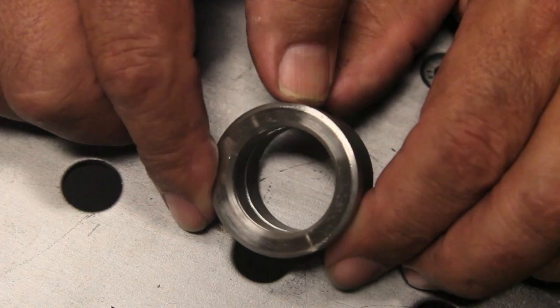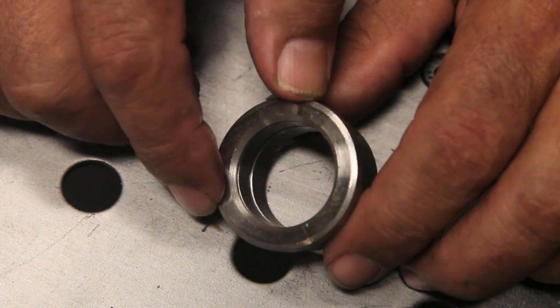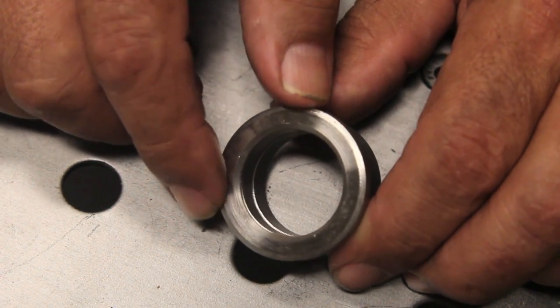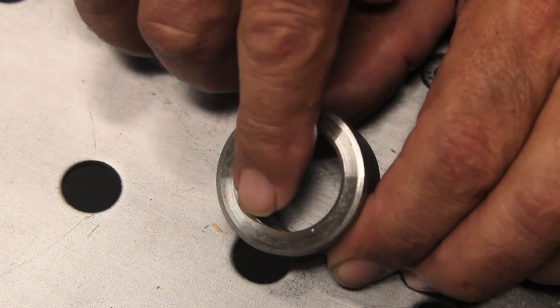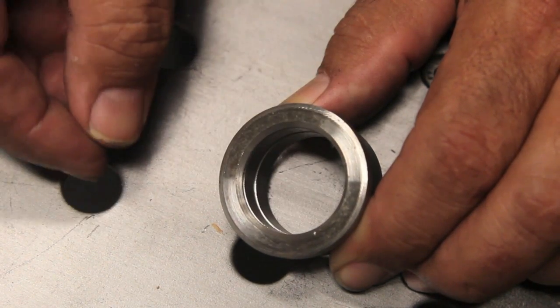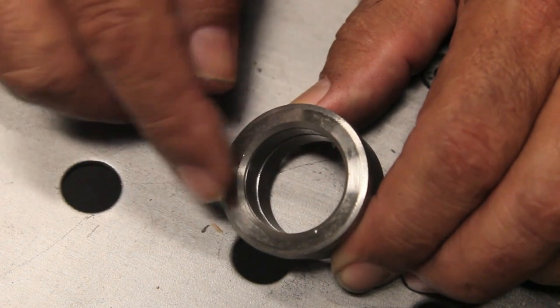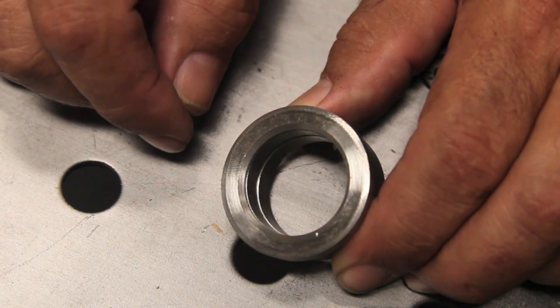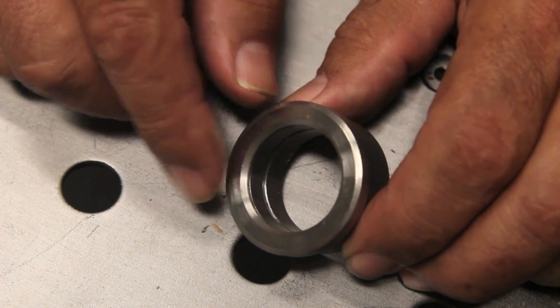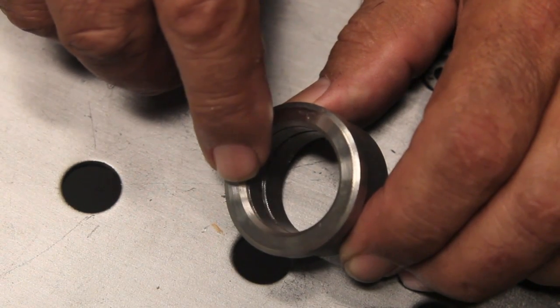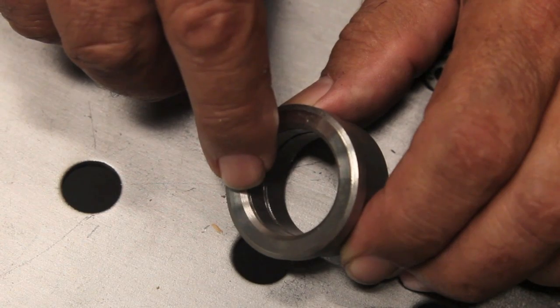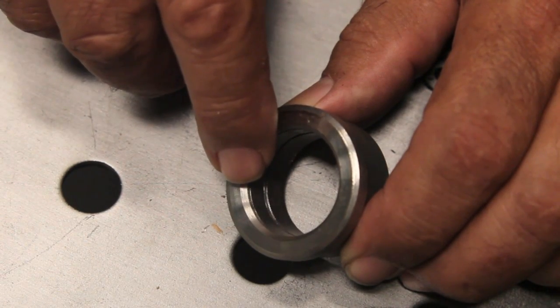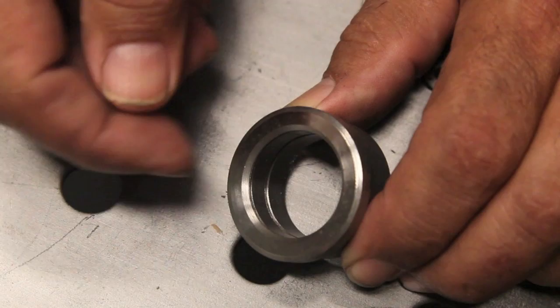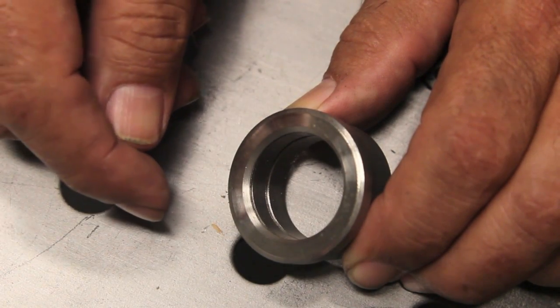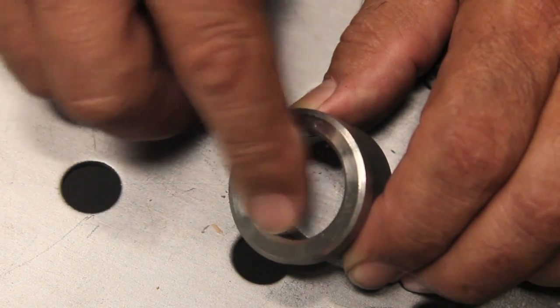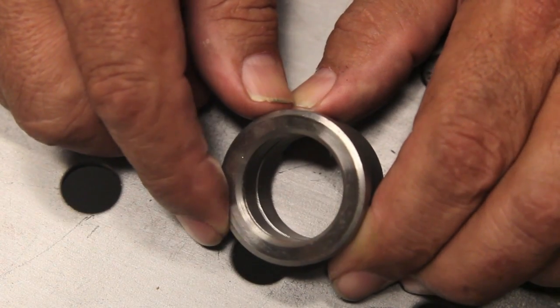Another example of practical application would be replacing metal that had been accidentally machined off. Like, for instance, this chamfer, this bevel right here on this edge. Let's say that was an accident and that was meant not to be there, and it needed to be a sharp edge for compliance to the drawing or something like that. Pulsing at 33 pulses a second will let me shape that bead and make a nice high crown bead where it'll machine off at a nice sharp corner. It'll control it and keep it from fanning out, wicking out, melting all the way over the corners and wandering and everything. It makes a difference.